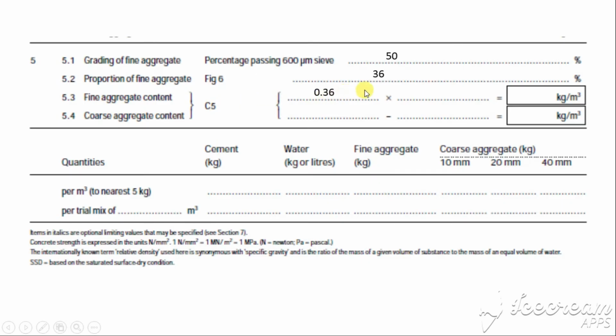0.36 times 1888, you will get the fine aggregate content 680 kgs per meter cube. Next, calculate the coarse aggregate content. Take the total aggregate content 1888 minus the fine aggregate content 680, you will get the coarse aggregate content 1208 kgs per meter cube.